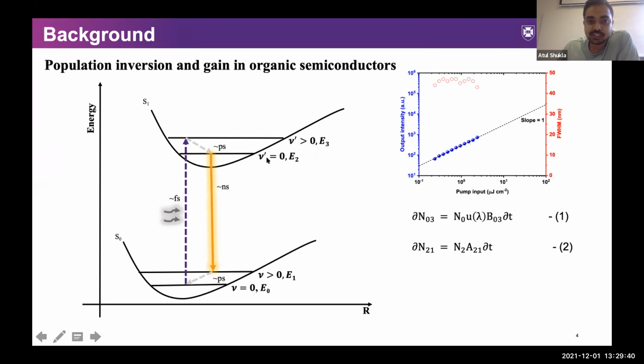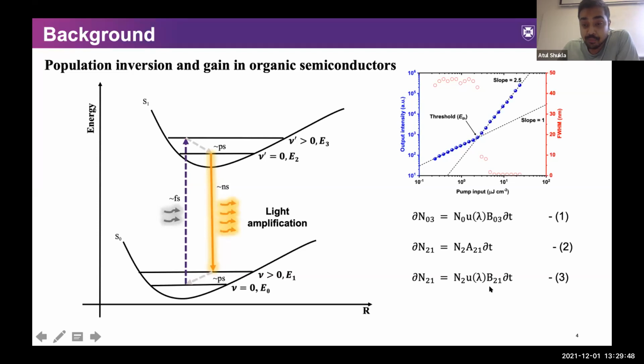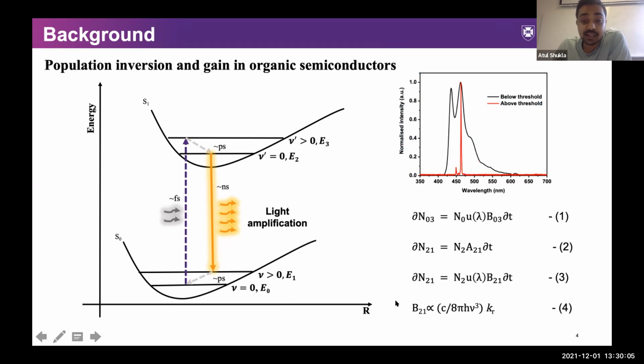But once we have enough population of these excited states, we can have stimulated emission, which is further governed by the Einstein coefficient B. Looking at these equations, if we want population inversion at low population density of the excited state, we want our Einstein coefficient to be as high as possible. In organic semiconductors, the Einstein coefficient is directly related to the stimulated emission cross section, which is further related to the radiative rate of the material. So for stimulated emission, we mostly utilize materials with high radiative rates. It is generally not possible to get stimulated emission with phosphorescence and TADF materials. While there have been some reports of stimulated emission from TADF materials, mostly we only use fluorescent emitters.